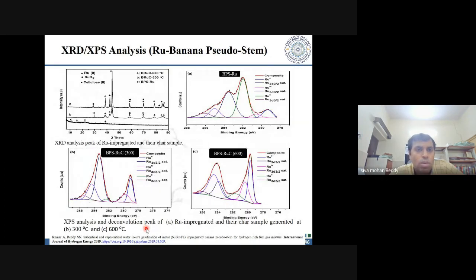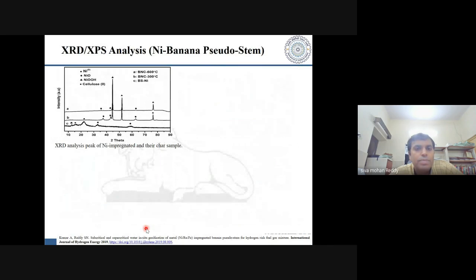Okay, so now let me just come back to our original discussion, where we are doing our XRD and XPS analysis. Now, if you look at the XRD profile after the hydrothermal treatment, you see that the peaks which are related to cellulose disappear over here.